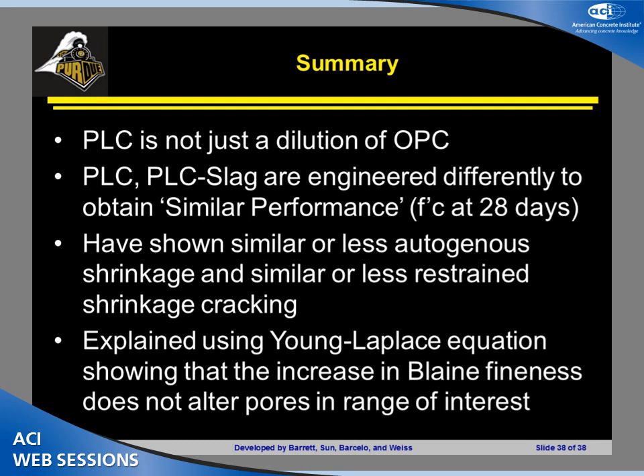I'm wondering, for one of the systems, we did the shrinkage test in a nitrogen environment. Is this particular system more susceptible to carbonation? The reason that the systems are done with a nitrogen purge is that if you take a small paste system and expose it to carbon dioxide, you're going to get carbonation shrinkage in addition to the water-based shrinkages that we're seeing. So it's fairly common when you do small samples like that, because they're sitting for so long, that you do them in a nitrogen purge. And a lot of the older literature that you'll look at does them in a nitrogen purge.